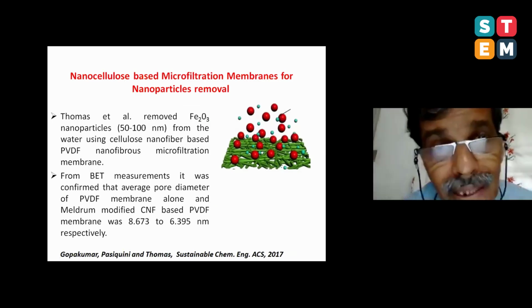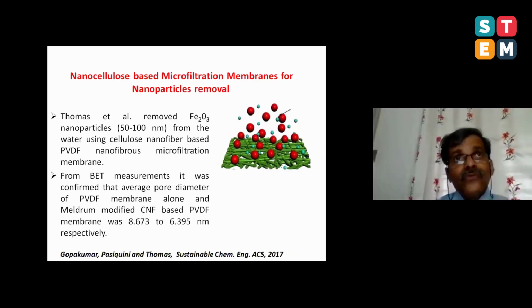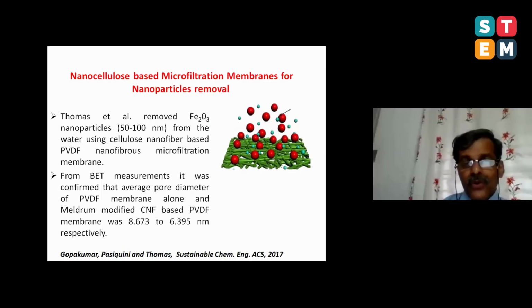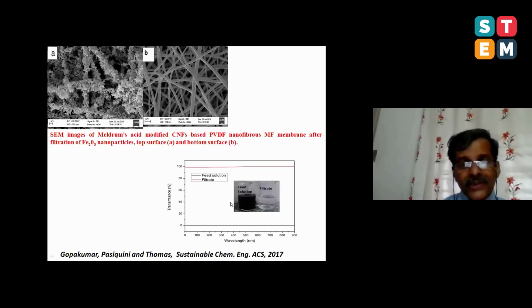Deepu and I, in my university, we also try to remove suspended particles based on cellulose extracted from agricultural waste. Look at this, this is our filter. The filter has been modified with nanocellulose. And we could remove suspended particles. You know, the water has a lot of particles. It could be nanoparticles, microparticles. So what we try to do is remove iron oxide particles from water in the range of 50 to 100 nanometer. I can show you our separation efficiency.